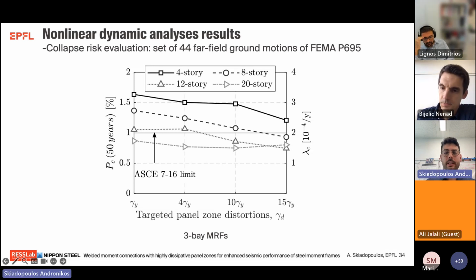Based on the collapse fragility curves and the hazard curves, we calculated this probability of collapse in 50 years, and we compared it with the threshold, the reliable limit of the American code, which is 1%. What we see is that conventionally designed moment resisting frames with elastic panel zones on the left side of this plot do not achieve this limit, contrary to our proposed panel zone designs that pass this limit. This example is of the 3-bay moment resisting frames because this design utilized deeper beam sections that increase the fracture potential in the connections.